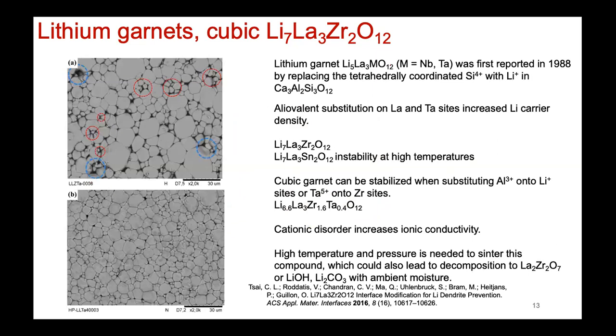So that's what people do. They'll start off with this material. Here, you could see some voids. And in this particular study, they looked at LLZO, although they put in a little bit of tantalum and niobium as well to increase ion conductivity. So you can see at high, so this is HP, so this is high pressure. They also sinter at a high temperature to densify the material. So you can see the voids have decreased, which is a good thing because then there are fewer low energy pathways for lithium filament to grow, which is desirable.